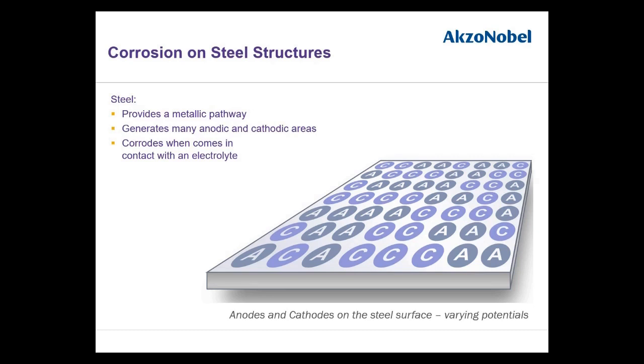Now, this is a very good potential for corrosion because the environment contains oxygen. There may be humidity, there may be salts. Easily it forms an electrolyte. So steel becomes very active from the moment it is manufactured. At high temperature, steel corrodes in the casting yard itself, and that bluish gray surface which you normally look on brand new steel is nothing but a metal oxide which is hard. That is nothing but mill scale.